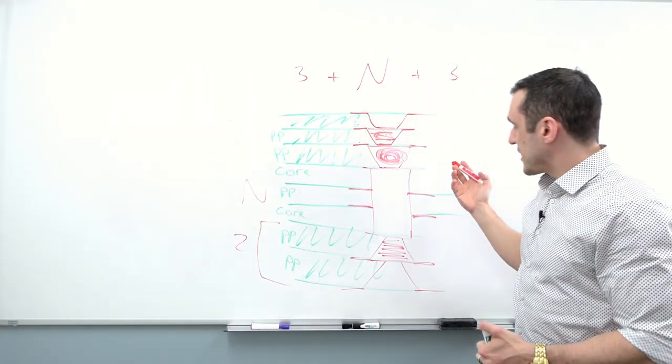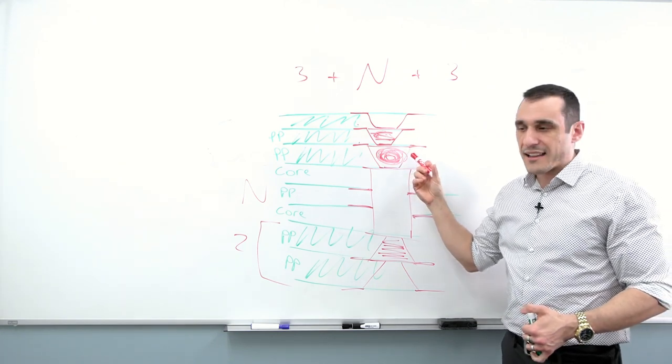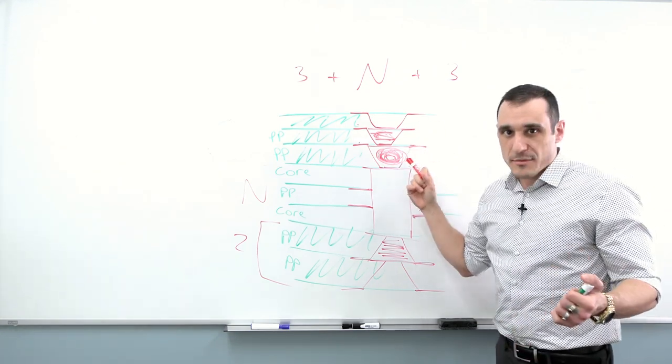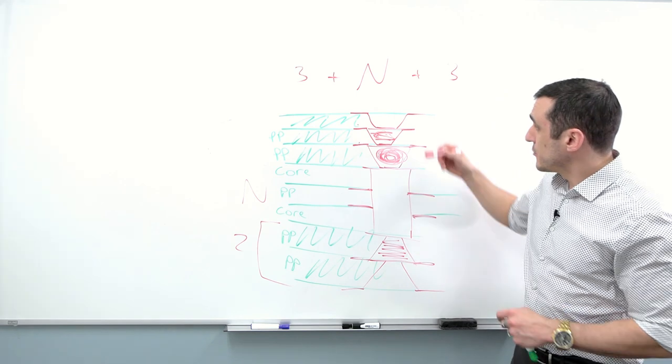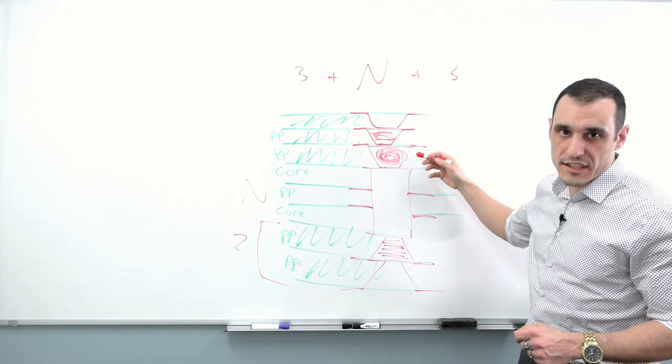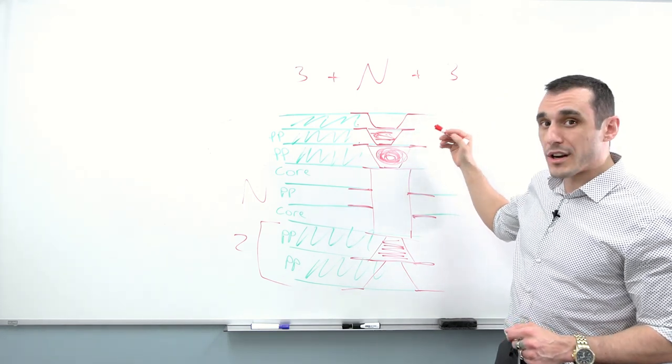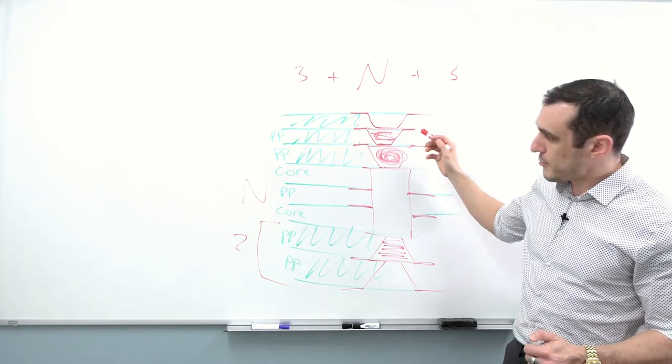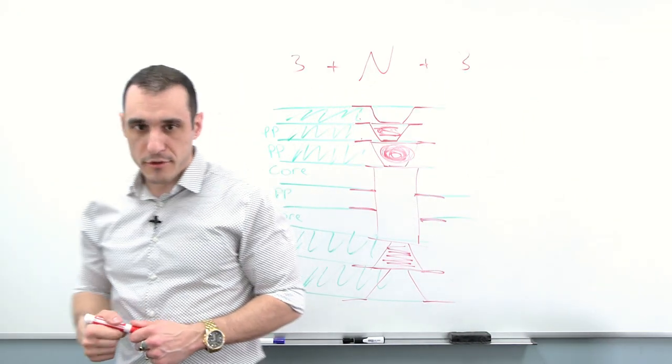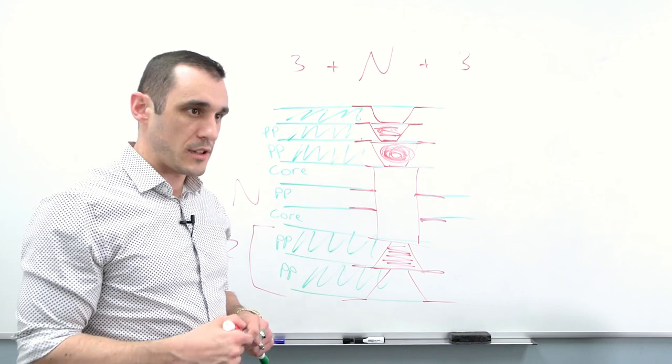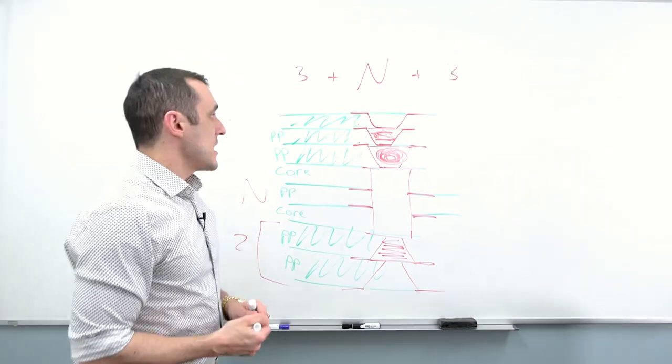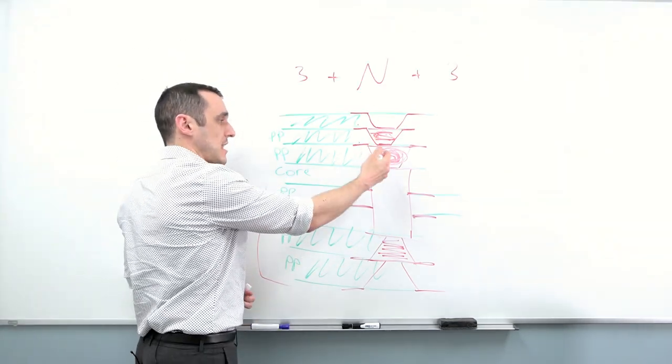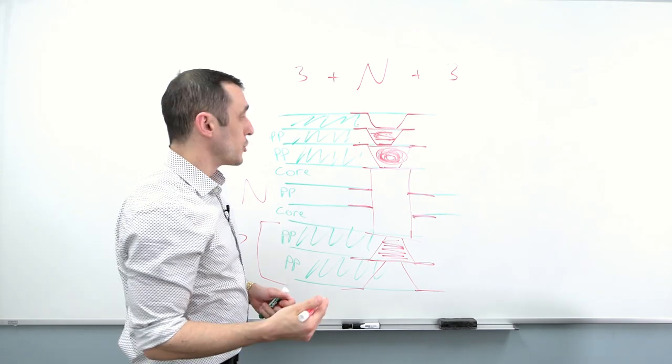They all apply here as well - it's just that this is all pretty much standardized. Now, the way that I've drawn this here, I've drawn these all as being stacked. However, they don't have to be stacked. In fact, with this arrangement of three microvias like this, you would not want to stack those unless your fabricator can demonstrate that they can put this through reflow reliably. One of the things that happens with microvias, or has been known to happen for the last 12 years or so, is that stacked microvias like this could fail during reflow.